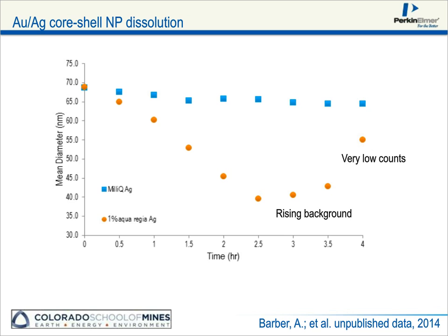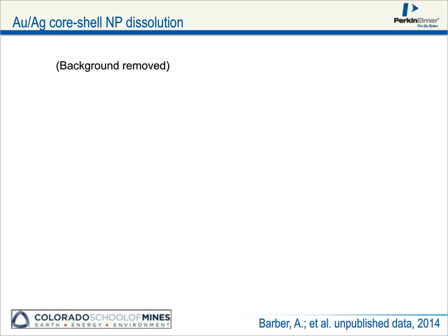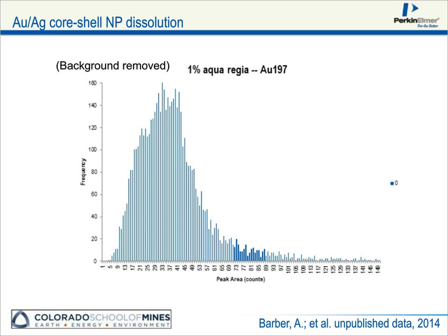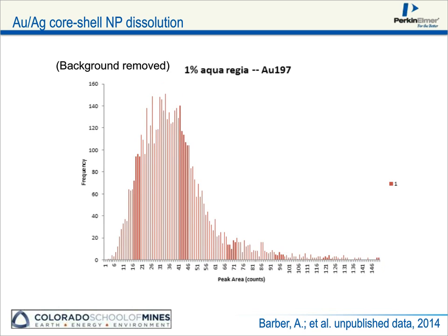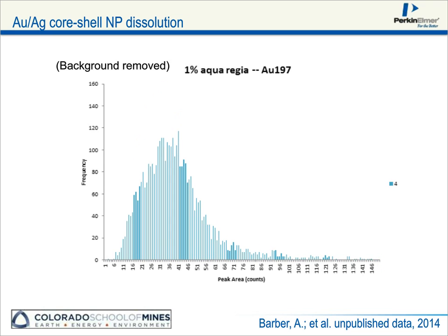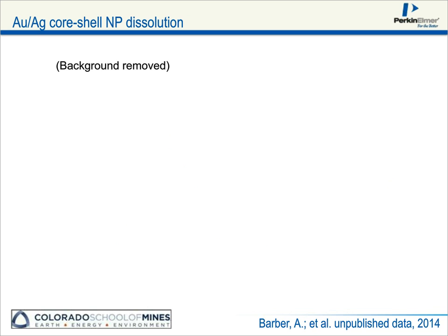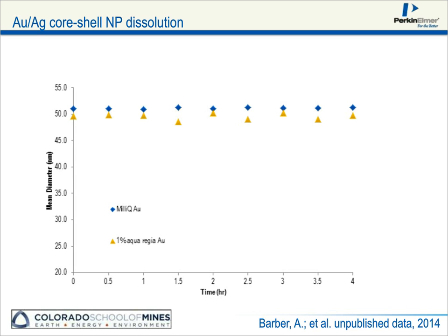So let's compare that to the gold core. Now we've got a distribution centered around 40 counts or so, and as we step through our time points, what you notice is it's not shifting in size. The gold core is protected from the aqua regia, but we are seeing substantial decreases in the particle number. So this is really highlighting what we need to know if we're going to also look at single particle not just as a sizing technique, but a particle counting technique. Again, because the gold is protected in both aqua regia and milli-Q water, the core doesn't shrink in size.